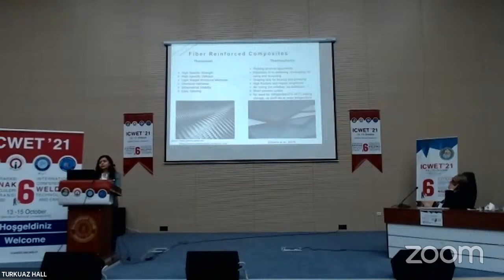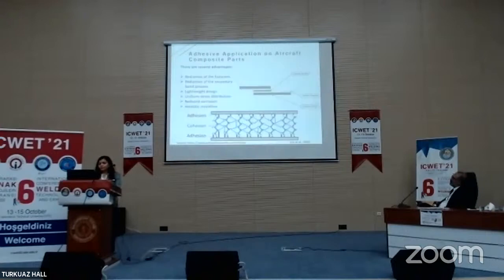Thermoplastics do not release gases or water vapor. Processing cycles are shorter because no cross-linking reaction is required like a thermoset. Thermoplastics do not need refrigeration, whereas thermoset prepregs do, and there is no shelf life for thermoplastics. Moving on to adhesive application.